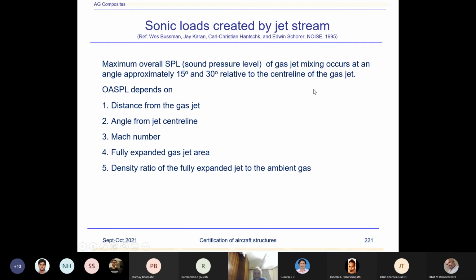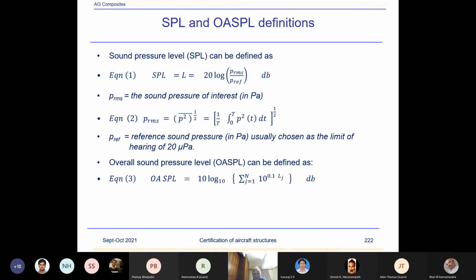So sonic fatigue loads are created by the jet stream. The maximum overall SPL, sound pressure level, of gas jet mixing occurs at an angle of approximately 15 to 30 degrees, which I said. OASPL will depend on distance from the gas jet, angle from the jet center line, Mach number, fully expanded gas jet area, and density ratio of fully expanded jet to the ambient gas. So many parameters. I won't go into the details.